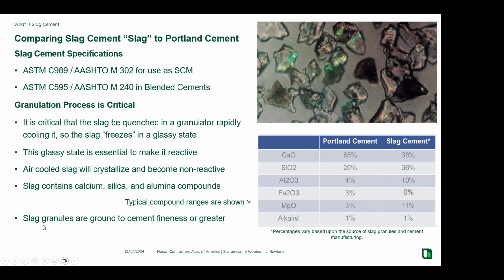Once slag cement has been ground, it is not inert. It will react by itself with water. It won't gain very much strength. However, in a concrete system with Portland cement or Portland limestone cements, it is very beneficial. And most ultra high strength or very high strength mixes will utilize slag cements in them because they're so beneficial for the mix.